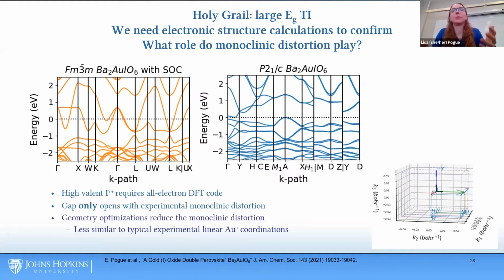And eventual calculations had actually shown very good agreement between the calculated band gap and the experimental band gap that we observed. I used the delta sol method to do that. It was giving me about 1.1 electron volts band gap.